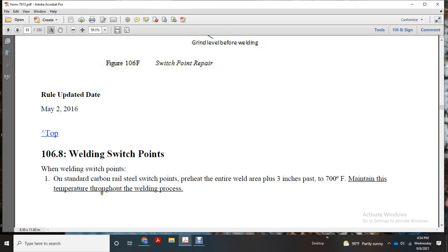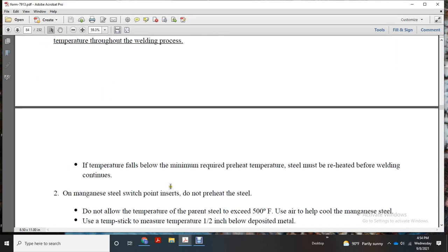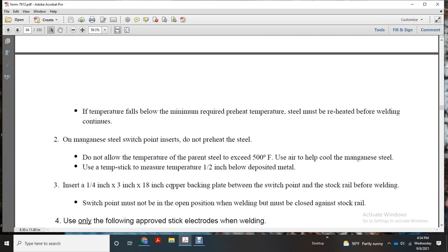700 degrees, maintain this temperature throughout the welding process. If the temperature falls below the minimum required preheat temperature, steel must be reheated before welding continues. On manganese steel point switch points, do not preheat steel. Do not allow the temperature of parent steel to exceed 500 degrees Fahrenheit. Air helps to cool manganese steel. Use a temp stick to measure 1/2 inch below the deposited metal.